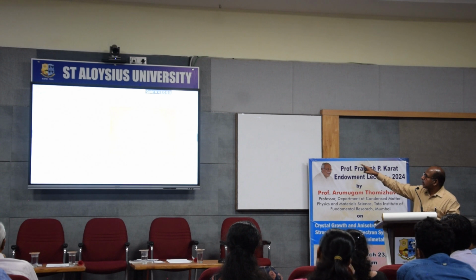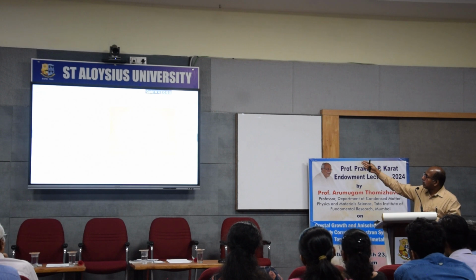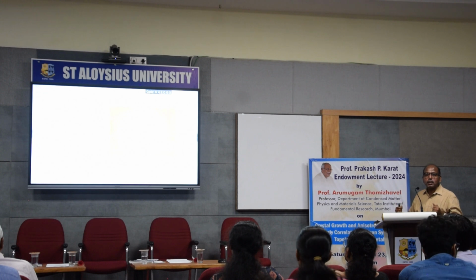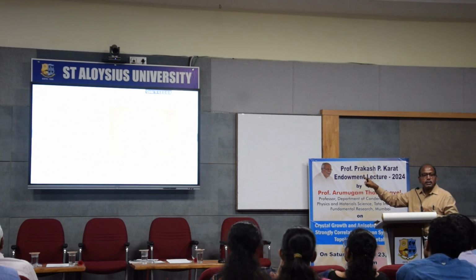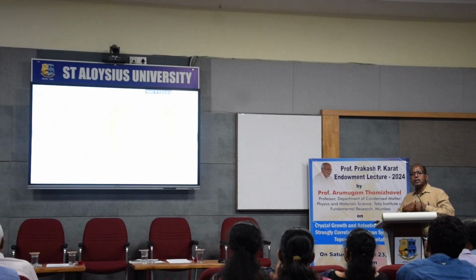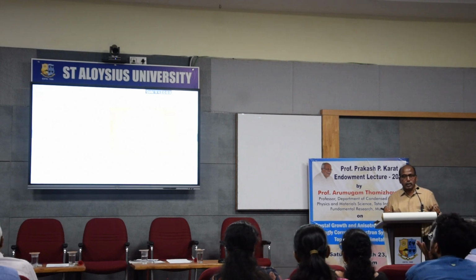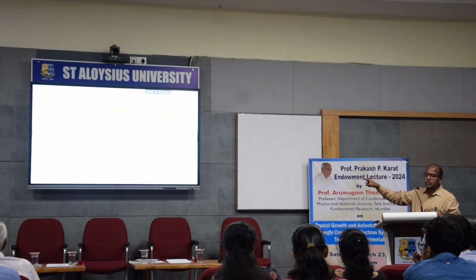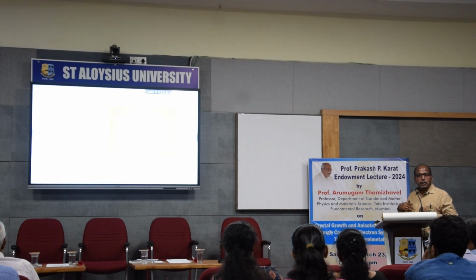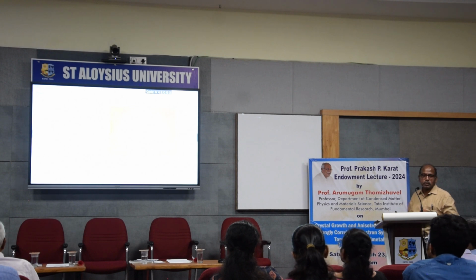If you see the previous graph, the top one is the RKKY interaction, where the system behaves magnetically. The bottom one is the Kondo effect. At one point, you see that the RKKY interaction and the Kondo interaction are equal and opposite. At that point, you see a quantum critical point. A quantum critical point means the system does not know whether it can order magnetically or not. This kind of quantum critical point appears at sufficiently low temperature and you see superconductivity in this. By studying this superconductivity, one can know the mechanism of superconductivity, so we can predict some new materials which can exhibit superconductivity.